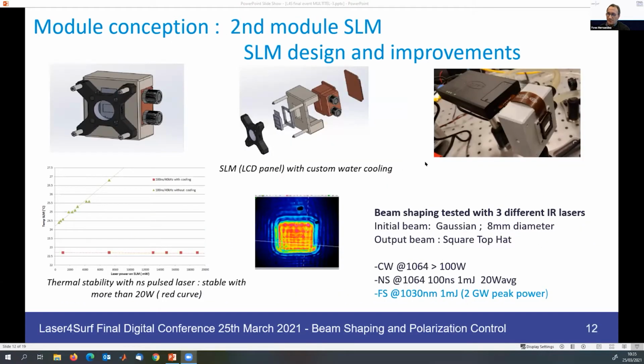The second system with the SLM, as I said, there are some limitations in terms of beam handling and power handling. You see on the curve on the bottom left that we made some tests at the beginning with a nanosecond laser, and we observed a rapid heating of the surface of the SLM. In order to avoid this problem, we developed just a small system for regulation of the temperature of the SLM and to control the temperature. As you can see in the curve in red, this temperature was kept very constant in function of the power injected on the SLM.